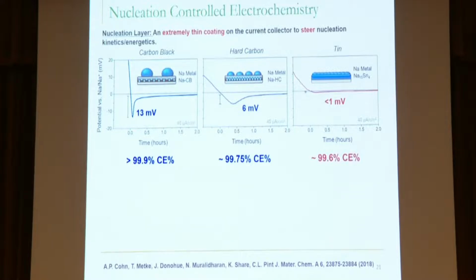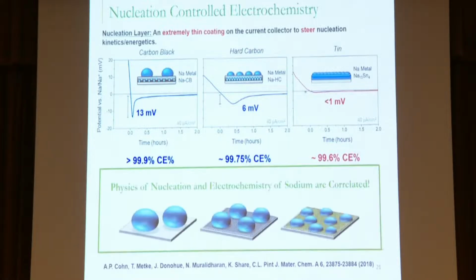They're friends. They like to hang out with each other. That's 99.6% coulombic efficiency, much better. Then we moved to different types of carbons, and we finally got to this carbon. It's a turbostratic type of carbon, carbon black. And we actually were able to achieve above 99.9% coulombic efficiency for this. That's charge efficiency, which is at a point where, hey, now we can call this a real industry competitive anode material for the system.